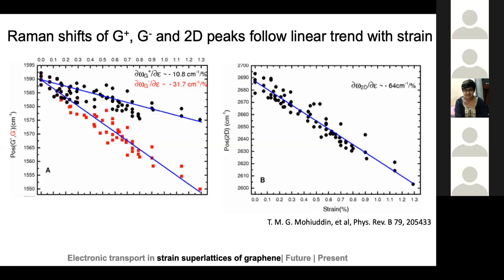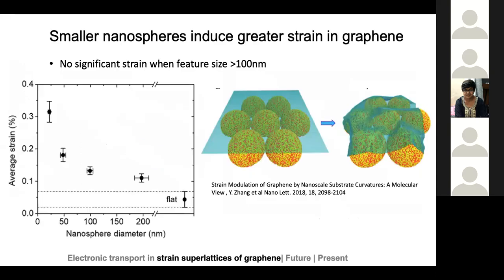Okay, so now we have some way of measuring strain in the system. You need to keep in mind this is the average strain over the system, so the local strain might be higher. What we are measuring is the average strain over a region of this graphene on nanospheres. And what was observed was that the average strain slowly decreases as the size of the nanospheres increases. And beyond 100 nanometers of diameter, there is hardly any significant strain left in your system. This is important. So in order to see effects of strain superlattices for such a system, the size of the features needs to be less than 100 nanometers or so.